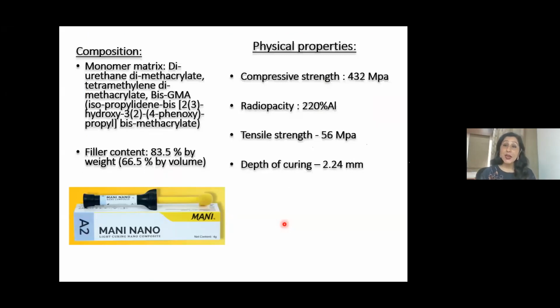The compressive strength is 432 MPa, which is more than microhybrids. But remember, my dear friends, when you want opacity, when you want extreme color changes, then microhybrids will help you. And here in Mani Nano, what you need is wherever you need good strength, wherever you need great luster. So in anterior posterior restorations, you can give Mani Nano. The depth of cure is 2 millimeters. Remember to place it in 2 millimeter increments only.